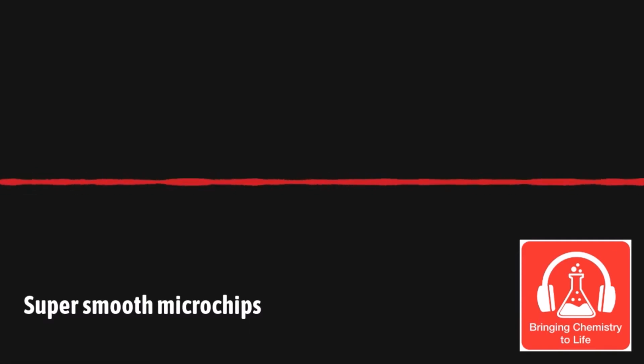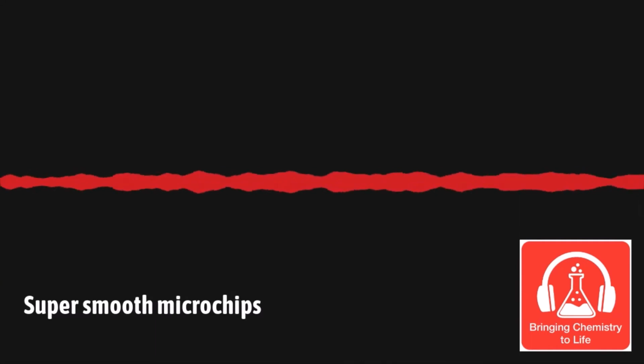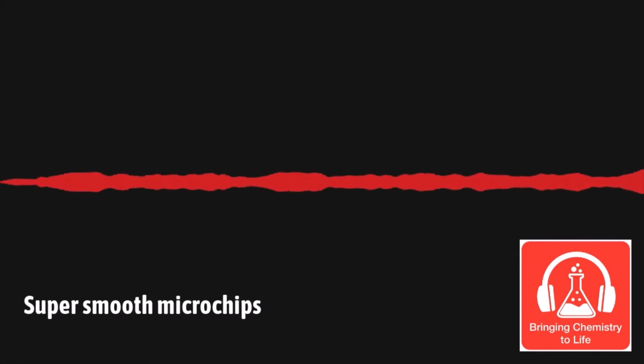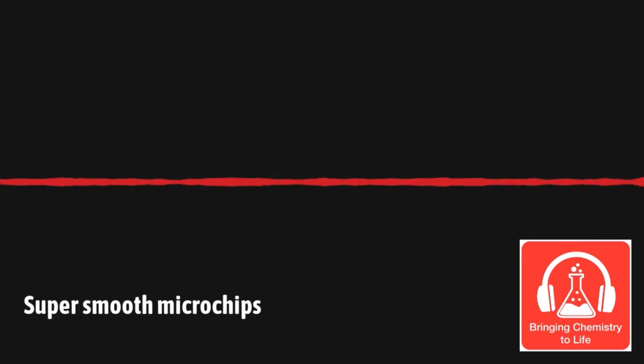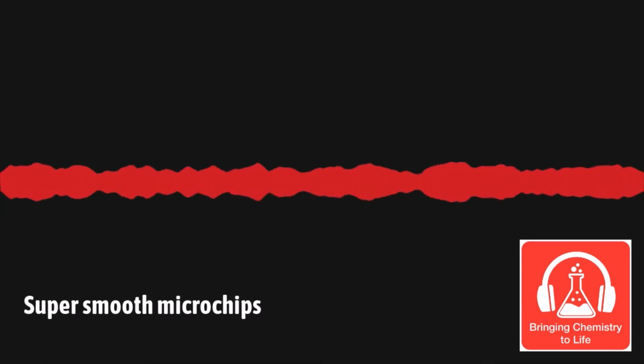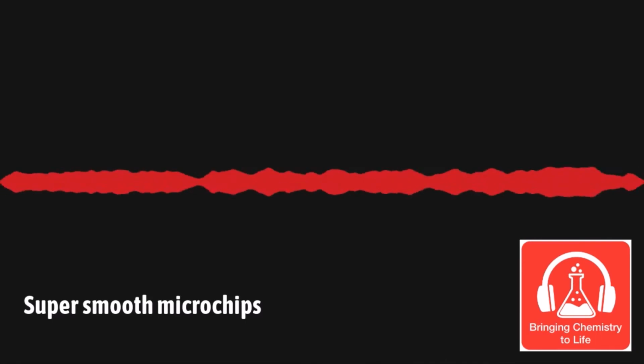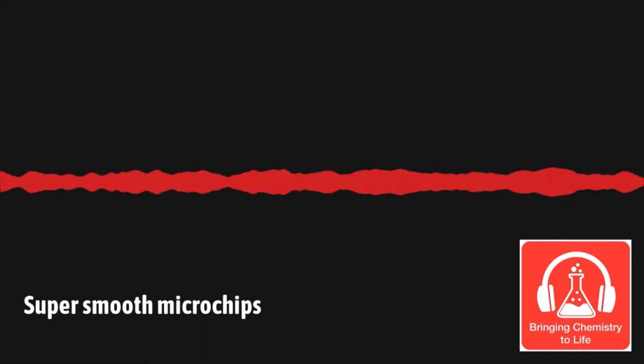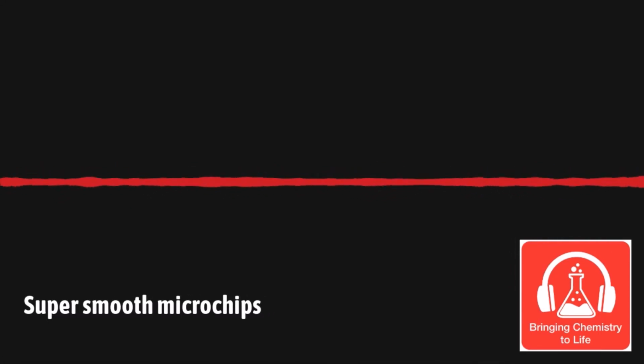I expect this to be a sort of emulsion because you have solid materials, you have liquid materials, and probably materials that might not mix very well with each other. Is there any specific solvent that is used to combine the ingredients together, or how does it look? We typically use very discrete nanoparticles, and so typically we use colloidal silica or colloidal ceria, and that can be readily dispersed in solution, right? So we can add different types of dispersions if the slurry starts to settle. During the formulation process, we take that into consideration.